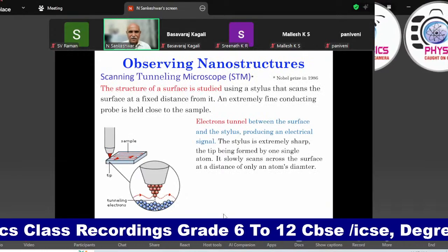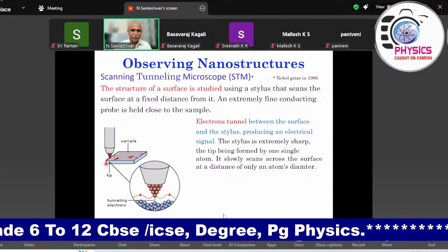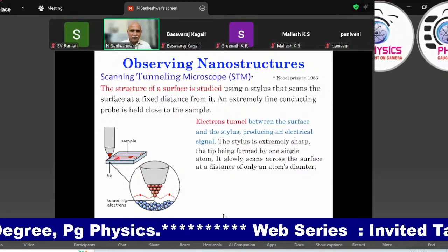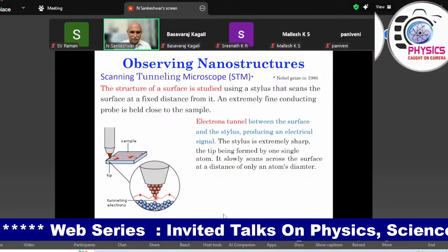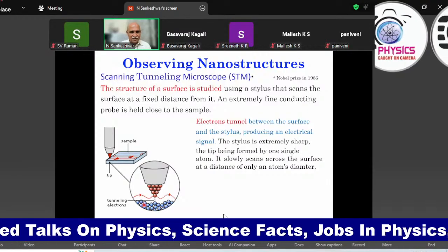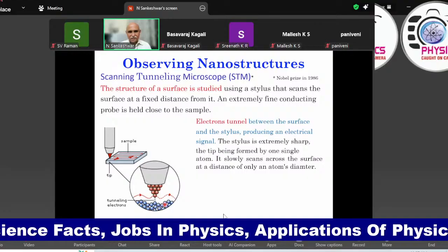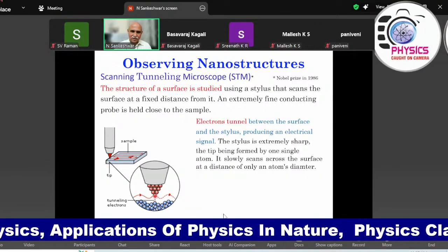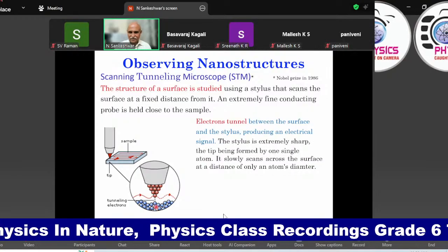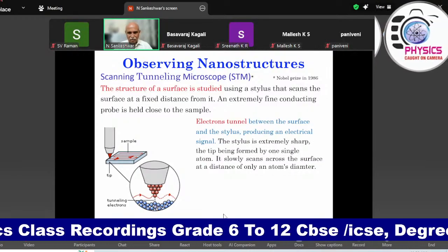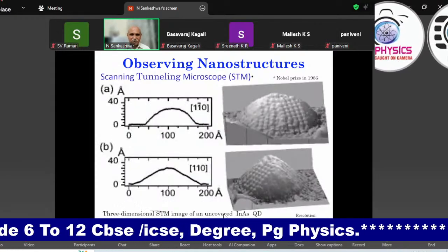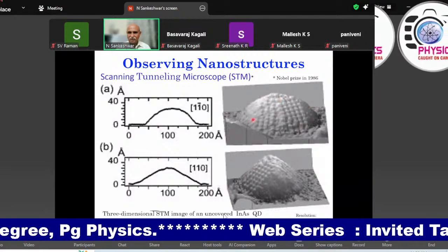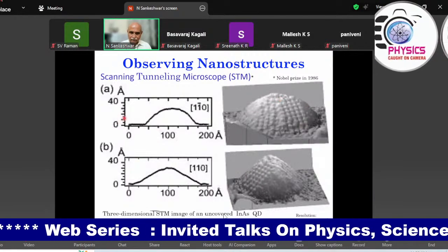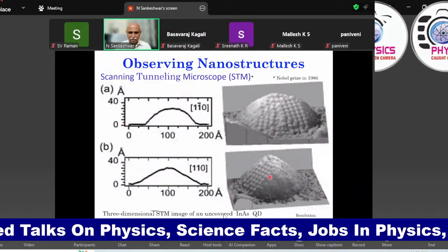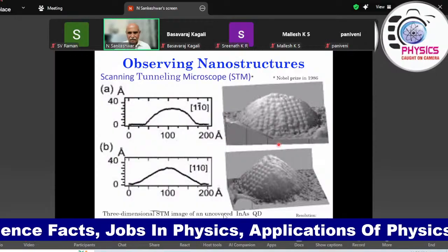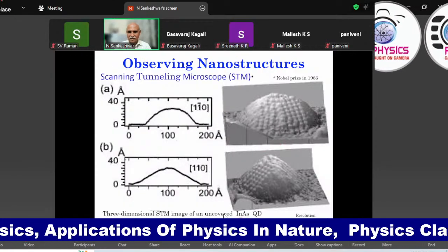So this is the example of your scanning tunneling microscope, where you have the tip of the probe, which can raster along the surface of this, and it can scan the surface, and it can find out what is the surface by the tunneling of these electrons through the tip and the atoms which are there on the surface. So that's why it's called the tunneling microscope. I'm not going into the details. So the effect of this is you can get a picture of what is the surface to the extent of even angstroms. You can see this is angstroms. This is also angstroms. So you can even see the atoms there. So this has been done for indium arsenide quantum dots.